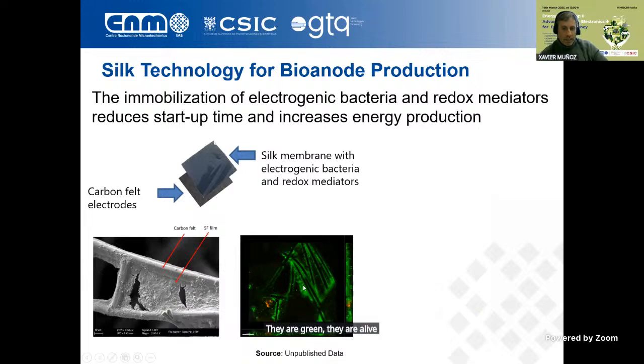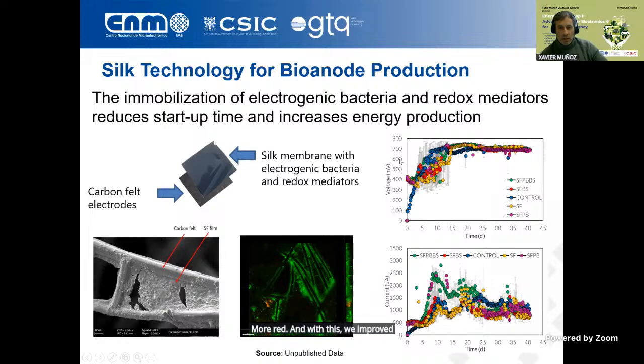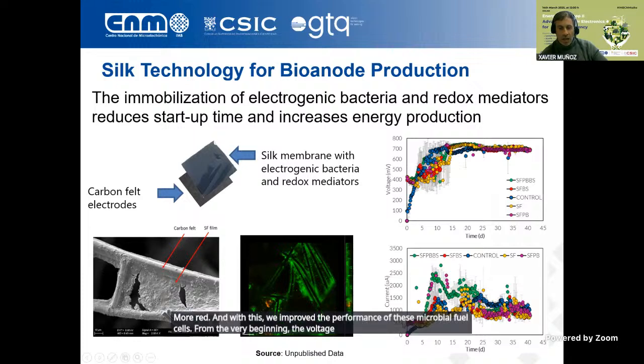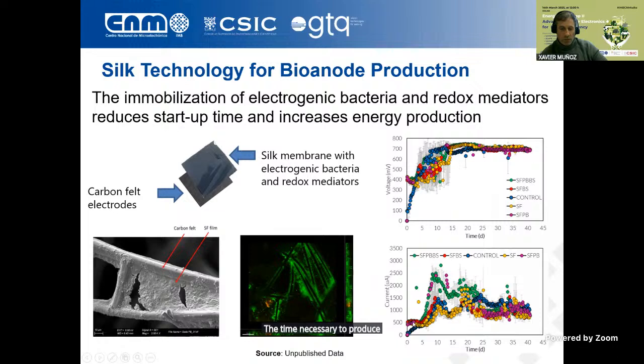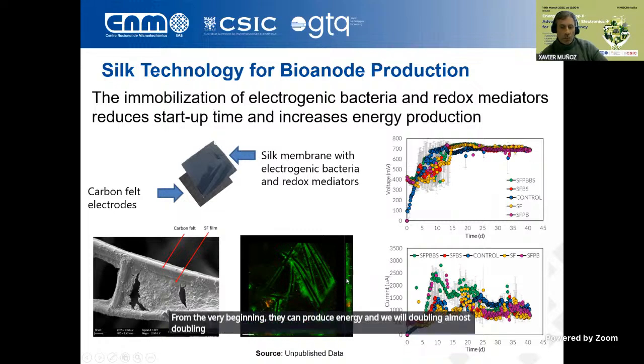With this protocol, if they were dead, they would be something like this, more red. And with this, we improved the performance of these microbial fuel cells. From the very beginning, the voltage was much higher, also providing energy in less time. It was 4 days or 3 days, the time necessary to produce energy. Now we reduce this time even to 0 days. From the very beginning, they can produce energy, and we were almost doubling the current that it was supplying and also the power.